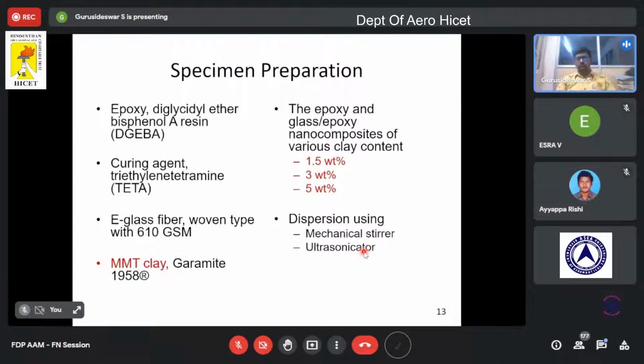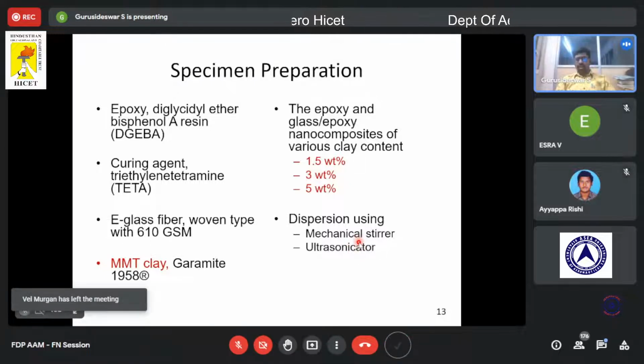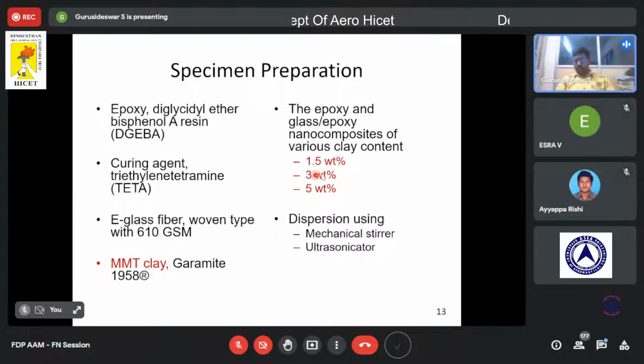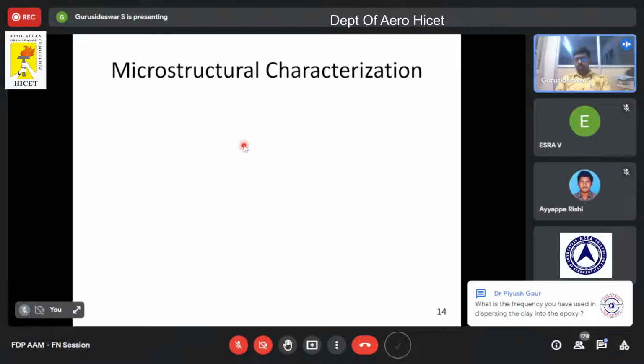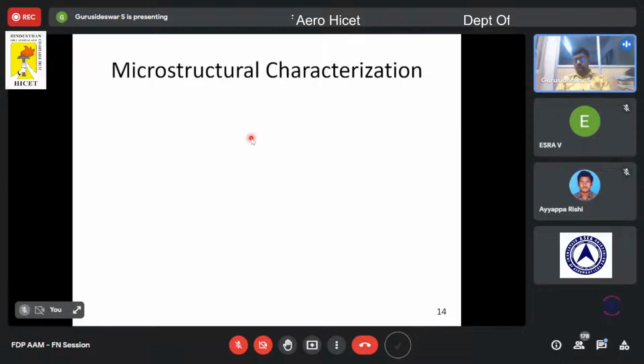And also we used an ultrasonicator for secondary dispersion. But during this dispersion, we had a challenge, because we know epoxy is a viscous liquid. So we faced a lot of challenges in dispersing this clay in this viscous liquid, but somehow we achieved good dispersion. So far I have talked about the preparation of the nanocomposite. Now let us move on to microstructural characterization.